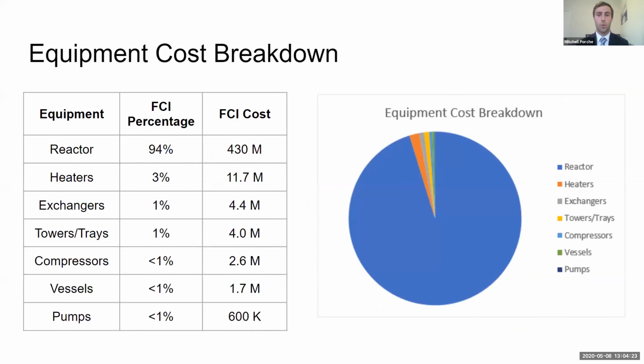Taking a look at our cost breakdown, you can see that our reactor is 94% of our total FCI. This is due to such a large calculated volume based on our volumetric flow rate of our feed and our chosen residence time. Another key factor to this price is our MOC, which is stainless steel because of the consideration of hydrogen embrittlement. You can see that our heaters go for 3% of our FCI, which we were able to reduce due to heat integration.